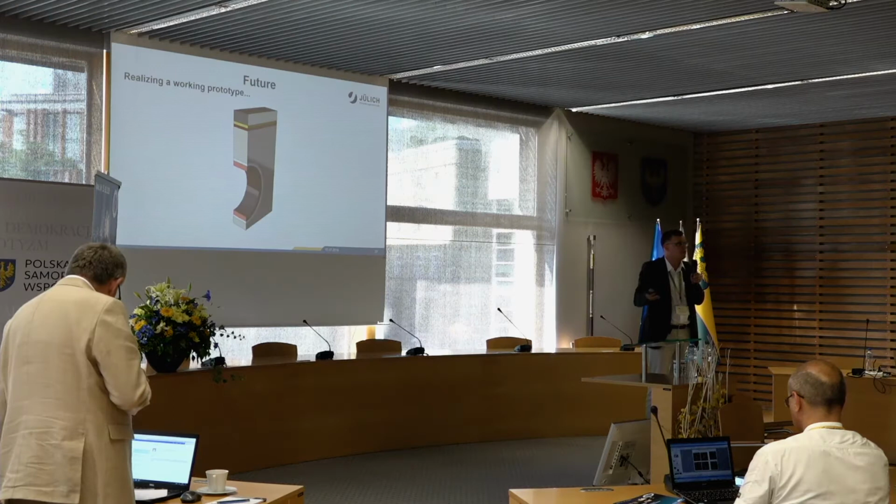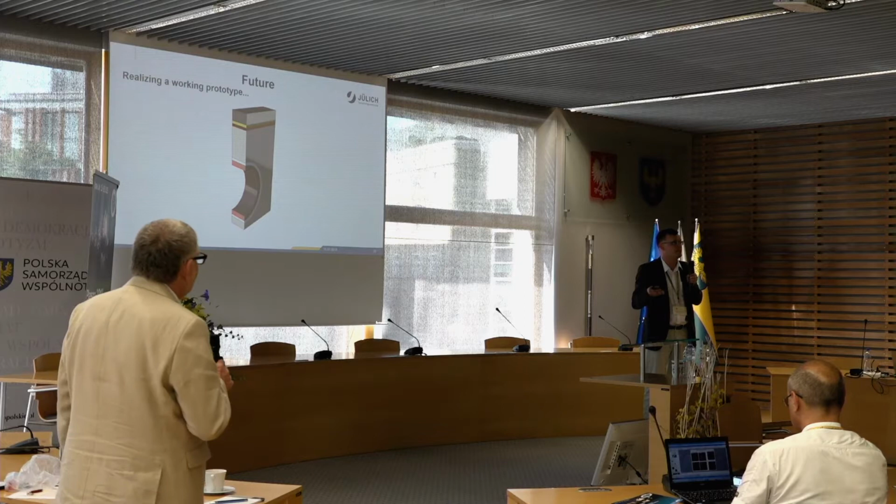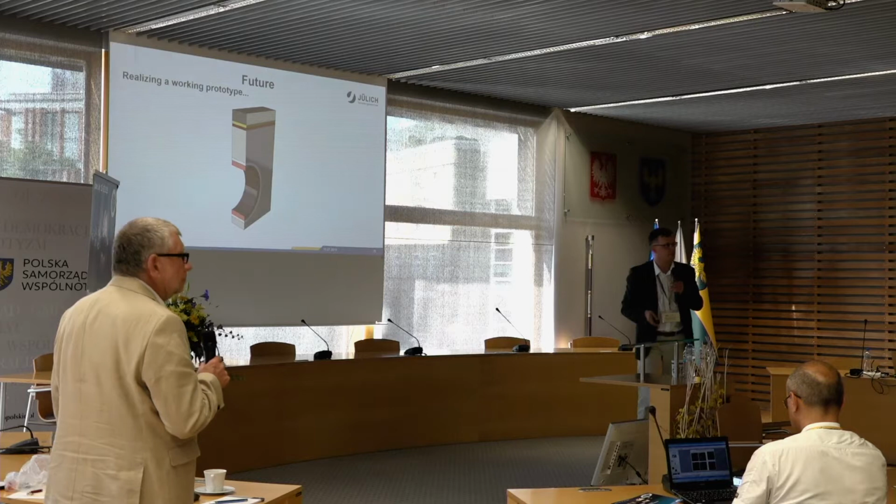What was, I would say, for us inspiring, these tungsten alloys, these are not the thin films deposited by magnetron deposition. These are industrial scale produced field-assisted sintered technology, which are available in centimeters of sizes. So at the moment we have 2 cm, but we already have a facility which makes 4x4, and another facility which goes 10x10. With 10x10, we're already covering all expected sizes, actually what we can assume. And we can go higher because it's now on high demand.